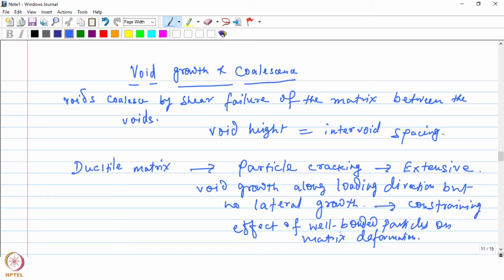And this has a huge significance in terms of the ductility. When the deformation of the matrix material is constrained by the presence of the particles, you can expect a higher ductility in the composite. Okay. So therefore, when the void nucleation occurs by the particle fracture mode, you can expect the hindrance to the coalescence by this constraining of the matrix flow, and this will lead to an increased elongation to failure and also higher toughness.